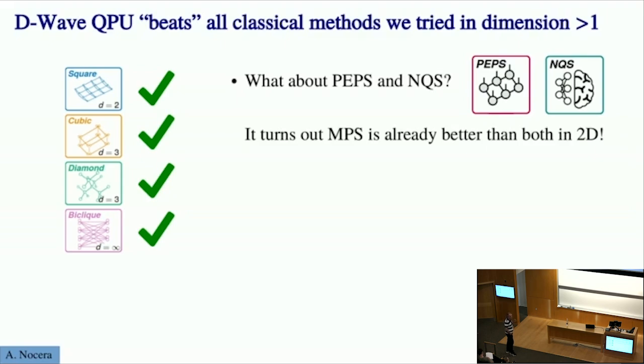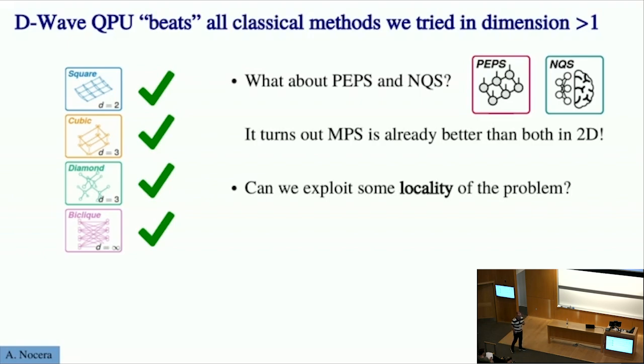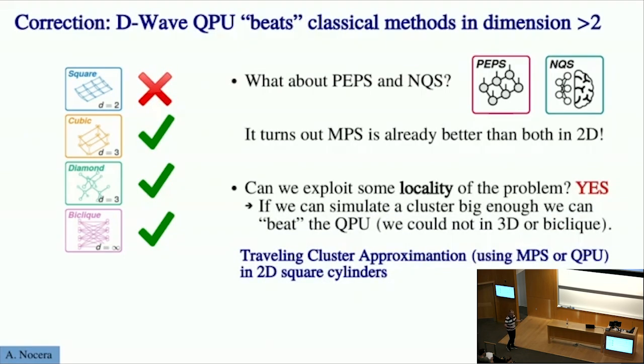And again, we described a single instance of disorder, right? So of course, we consider random couplings, and all these methods were tried for a single instance of disorder, not average ensembles. So what about some physical intuition about the problem? Can we exploit locality? I told you about this finite correlation length. The answer is you can exploit locality in this problem. And basically, we were able to show in the paper that if you can simulate classically a cluster big enough, of the order at least a few times bigger than the correlation length that is given by the Kibble-Zurek scaling, you can recover 2D results up to a very large scale, like up to hundreds of qubits, even classically. And we use this traveling cluster approximation, either using MPS as a solver or the QPU itself as a solver.